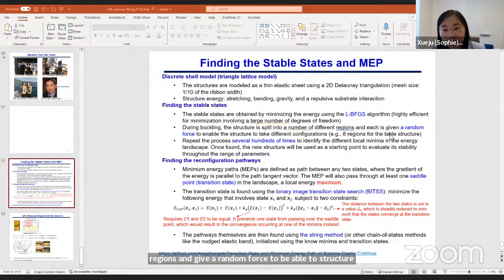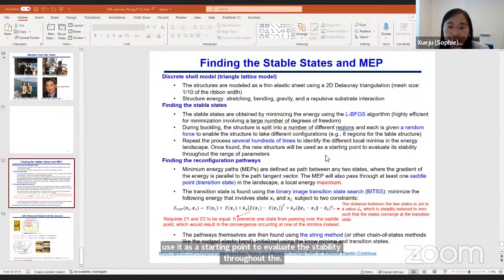For example, for the table-like structure, we use 8 regions, and then we repeat the process several hundreds of times to identify different local minima in the energy landscape. Once we found them, we use them as a starting point to evaluate the stability throughout the range of different design parameters. That's how.